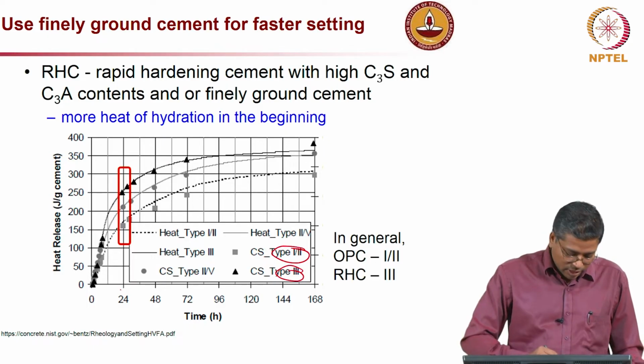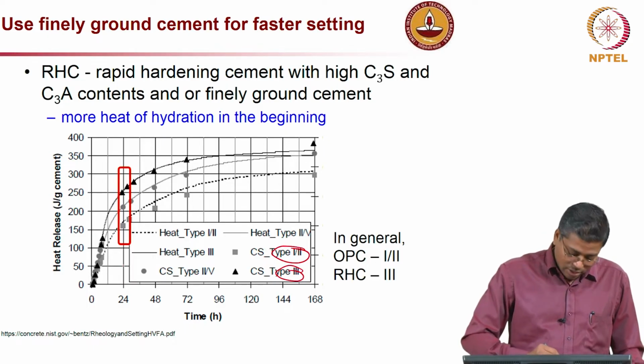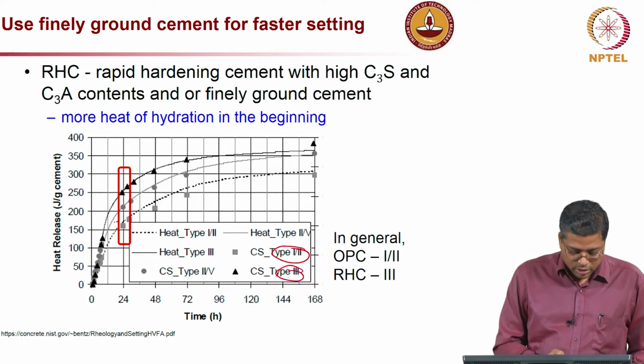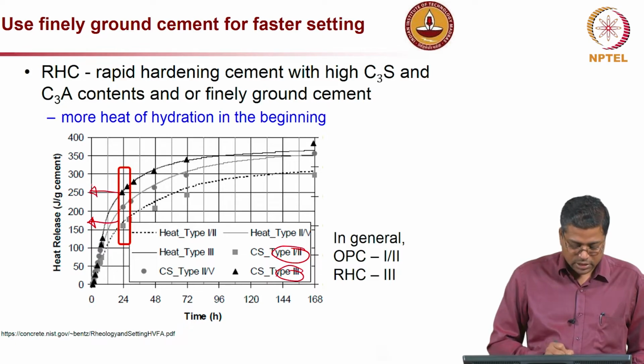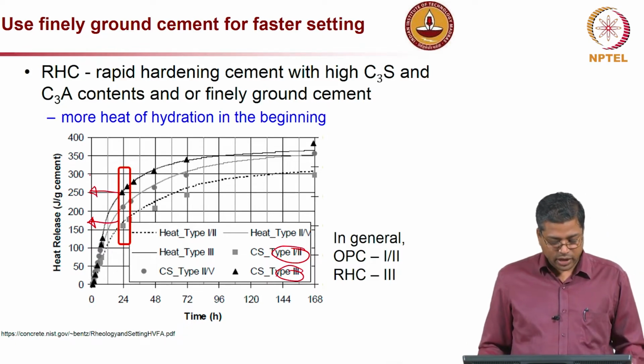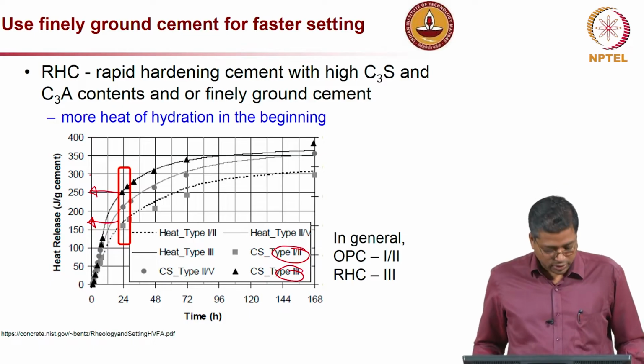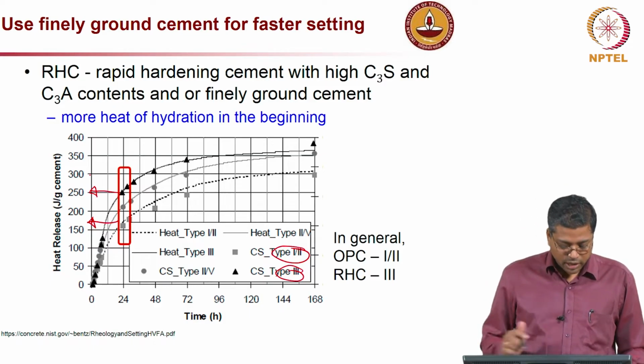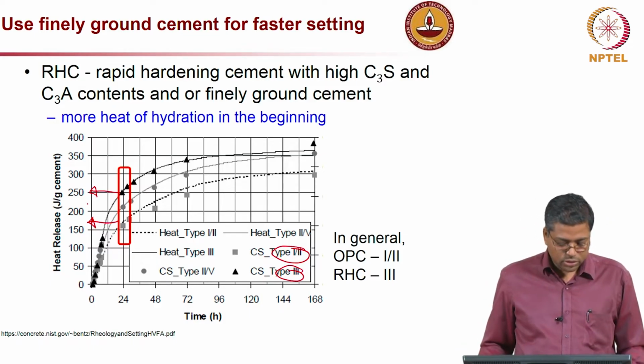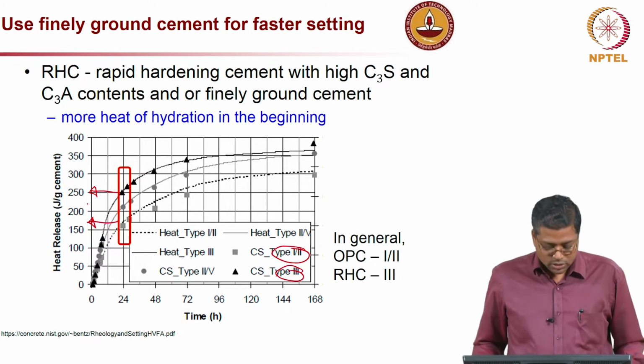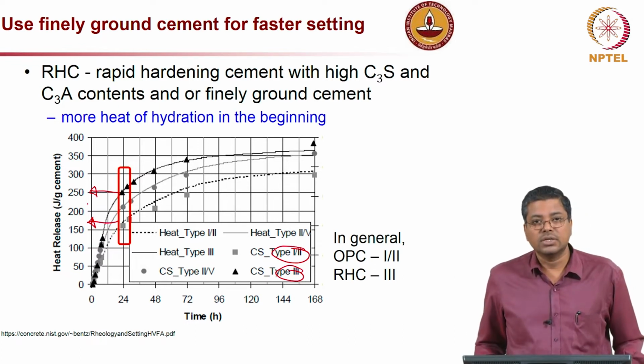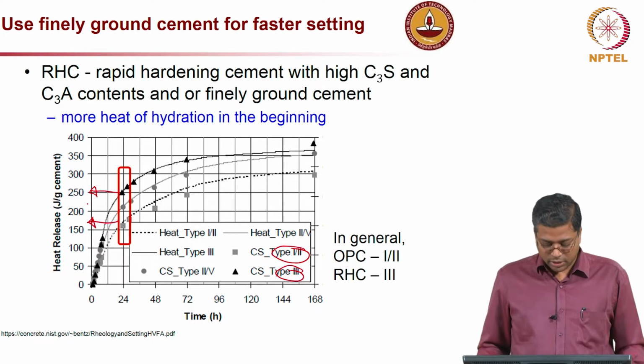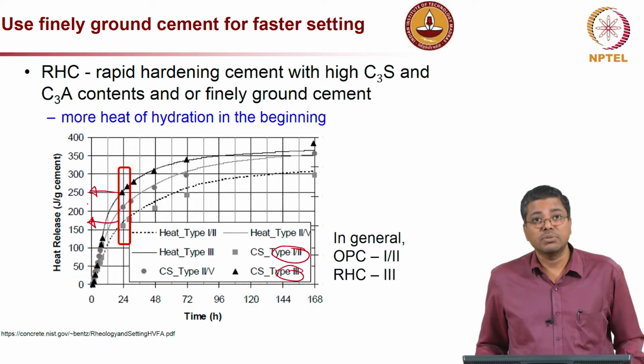So, you can definitely see within 1 day, that is 24 hours, a difference in the heat release, from about 175 to about 250, that is about 75 joule per gram of cement. So, that much heat release difference is there when you talk about different types of cement itself.